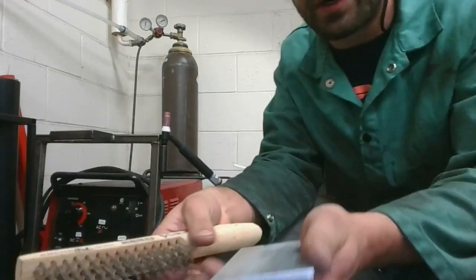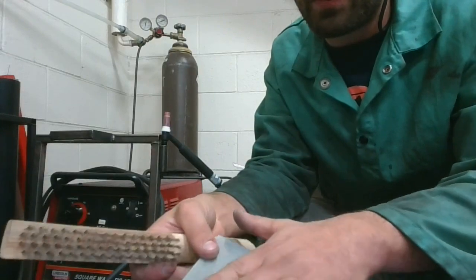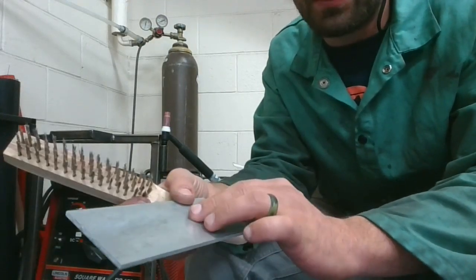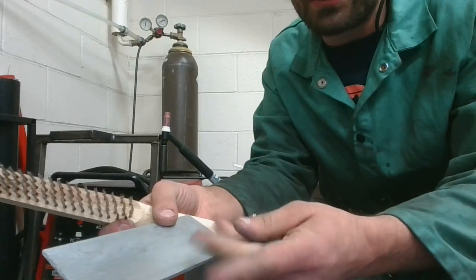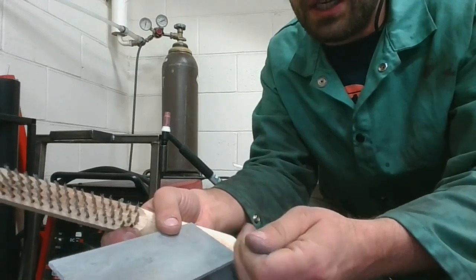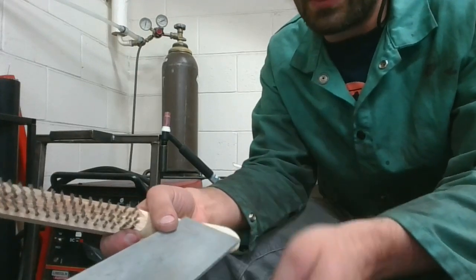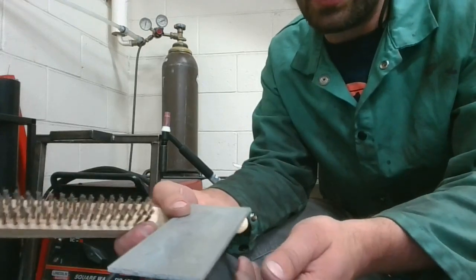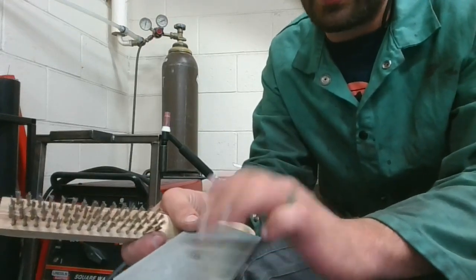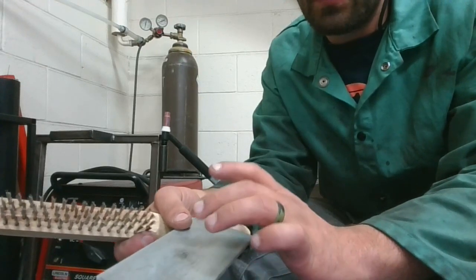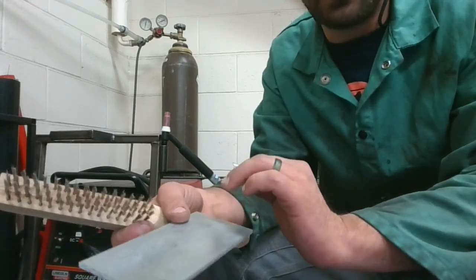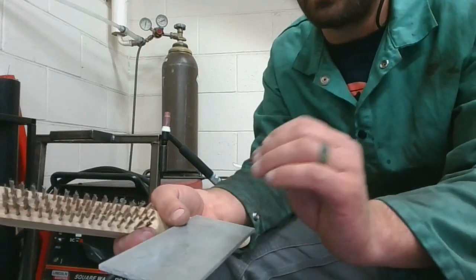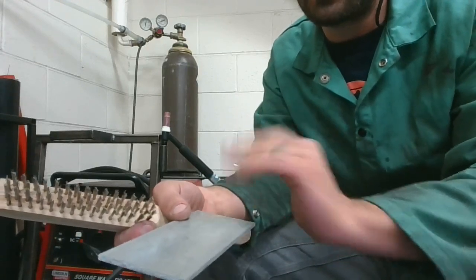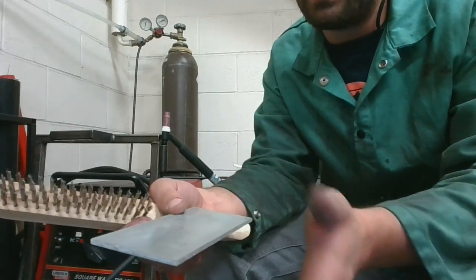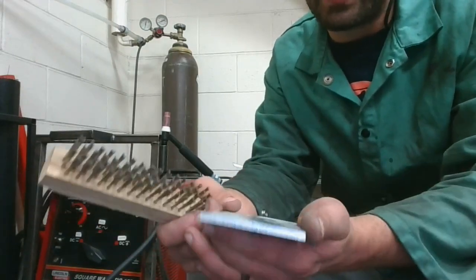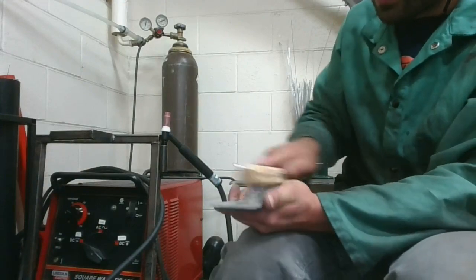The reason we want to brush this is we want to break up the oxide layer that's found on the top of this, because the aluminum oxide melts at about 3,800 degrees, whereas aluminum will melt at about 1,300 degrees. So you're going to have it way too hot by the time you get through the oxide layer to melt the aluminum. Typically, if you don't wire brush it, it'll get hot, hot, hot, hot, hot, and then as soon as you get through the oxide layer, it'll fall through the back side, just because of the way that it works. So just brush it up real quick. It doesn't take very long.